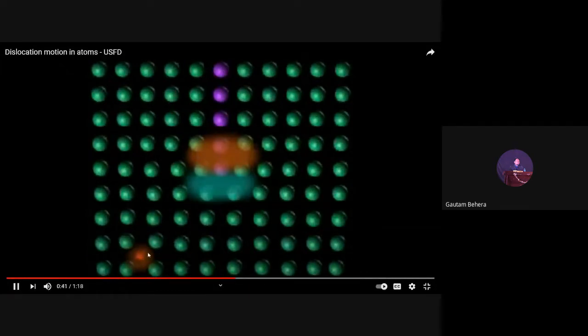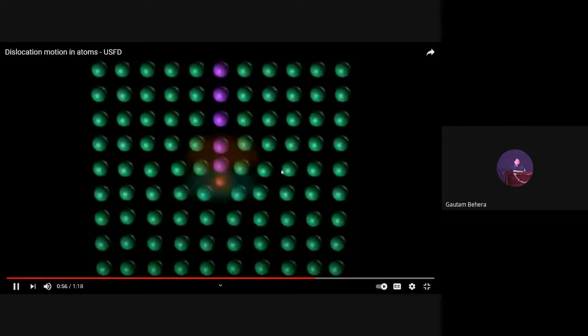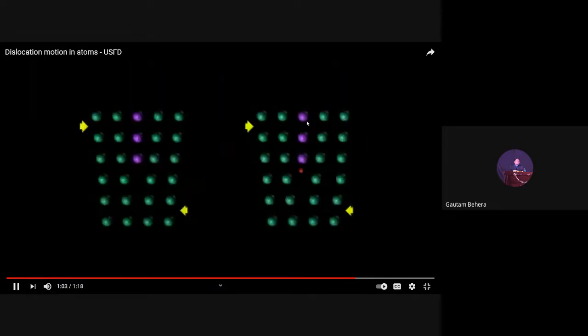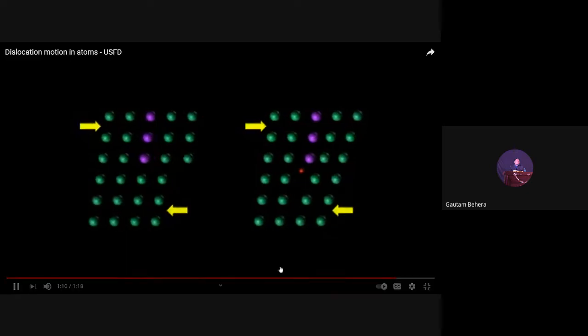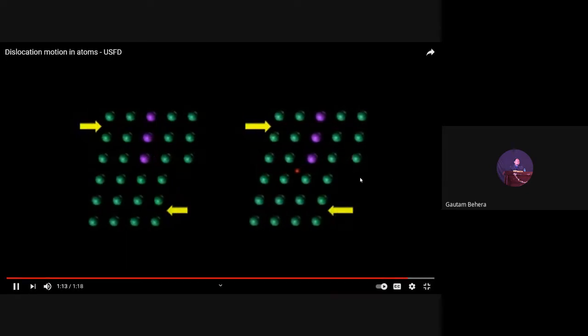This solute atom will wander or diffuse through the lattice, and will be attracted to the tensile strain region near the dislocation and just below the end of the extra half plane of atoms. The compressive strain field surrounding the solute atom will partially cancel the tensile lattice strains imposed by the dislocation. As a result of this relaxed strain field, a greater externally imposed shear stress is required to move the dislocation than is necessary in the pure metal. Macroscopically, this results in increased strength and hardness.